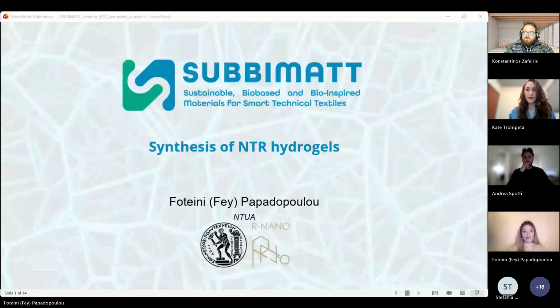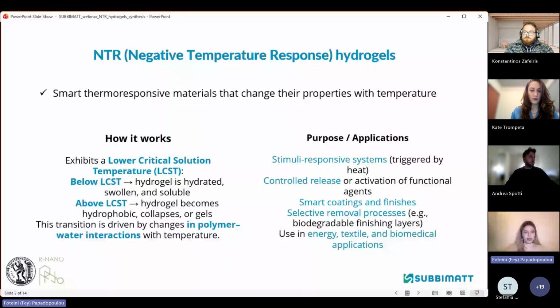Okay. So I'm going to talk about mainly the synthesis of those NTR hydrogels. As Kate mentioned, the LCST acronym stands for lower critical solution temperature. Below this temperature, the hydrogel is hydrated, swollen, and soluble. And above that temperature, the hydrogel becomes hydrophobic, collapses, or turns into a harder gel. And this transition is mainly driven by the water and polymer interactions with the temperature.